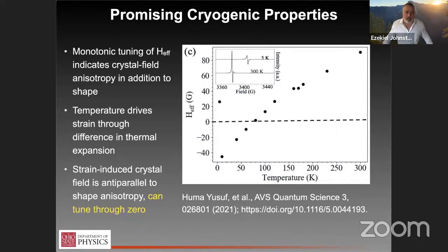So the second question, about the magnetic resonance field. The temperature dependence depends strongly on the material. You might see a slight increase in M_S as temperature decreases if you're looking at a metal. Right, the M versus T is pretty flat, and that saturation magnetization is ultimately what's going to control the magnetic resonance frequency.